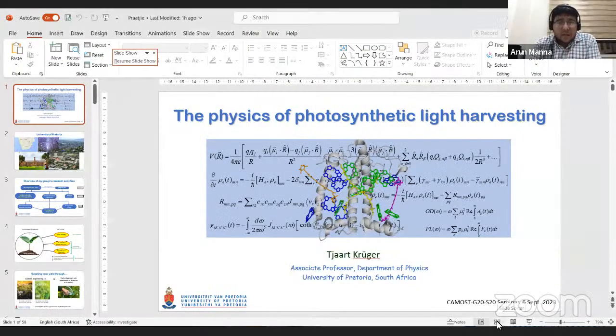In the examples that I showed of the light harvesting complex, in that case, there was a mixing between the exciton and the charge transfer states. So because of this mixing, you still have oscillator strength from the excitonic state, and that leads to fluorescence. Okay. And you get some quenching because of the involvement of the charge transfer state. So to say it technically correctly, if you remember the one equation that I showed, maybe I can just quickly get back to that. I think it's like a coefficient, the state 1, state 2 mixing that you talk about.